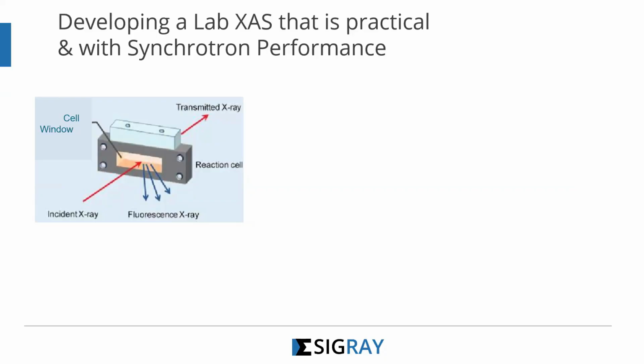So if you are looking to develop an XAS tool that is practical and has synchrotron type of performance, so you don't have to always run to the synchrotron to do those studies, then there are certain, let's say, criteria that might be useful. And those are the same criteria that Sigray has been using as we started to commercialize and develop this tool. The tool must be able to do transmission measurements. This means you have a sample in, the X-ray must be able to penetrate it, and you have a detector that measures the transmitted X-ray absorption spectrum. You must be able also to look at the fluorescence side under the reflection mode.